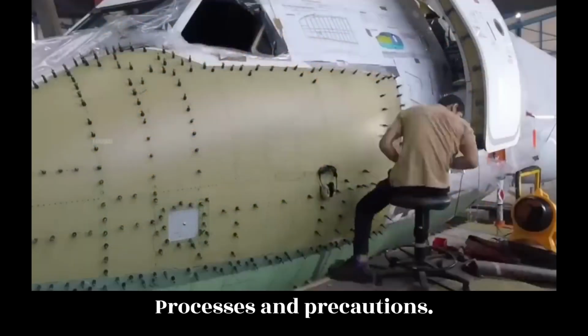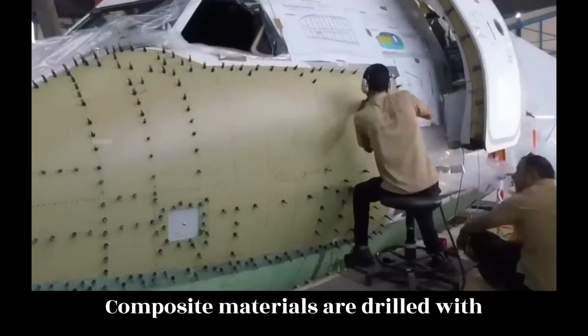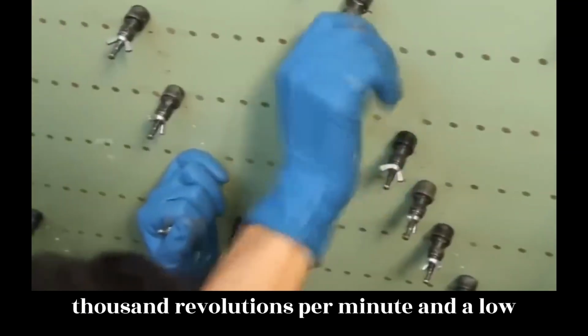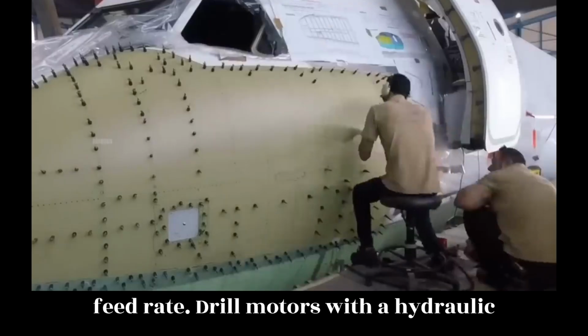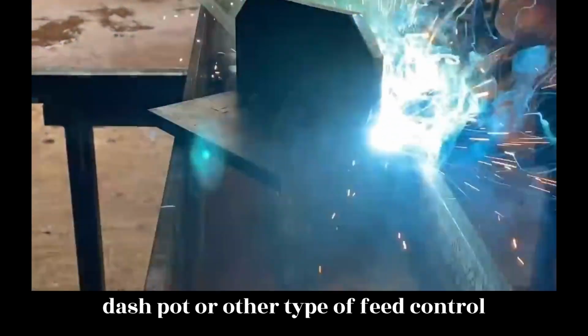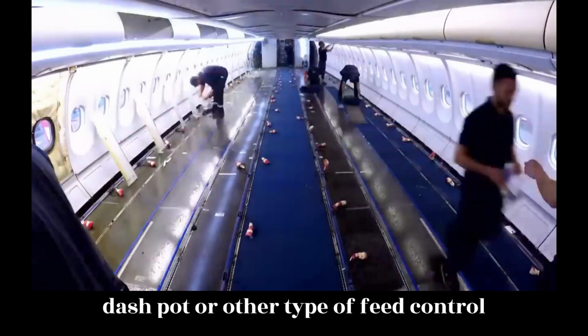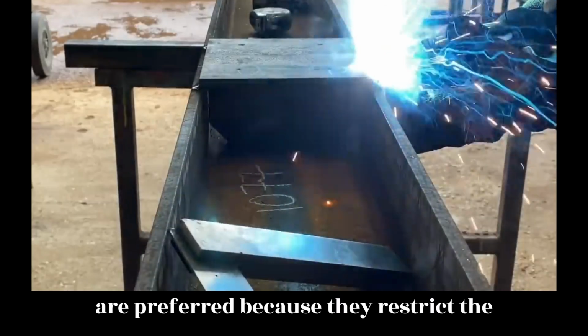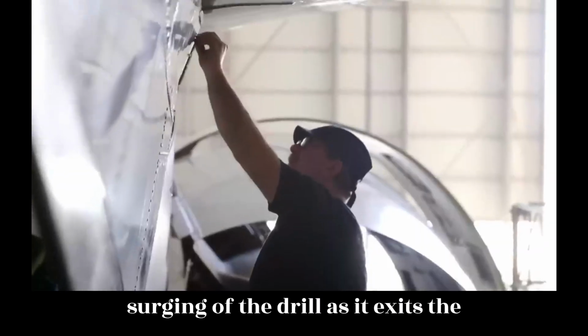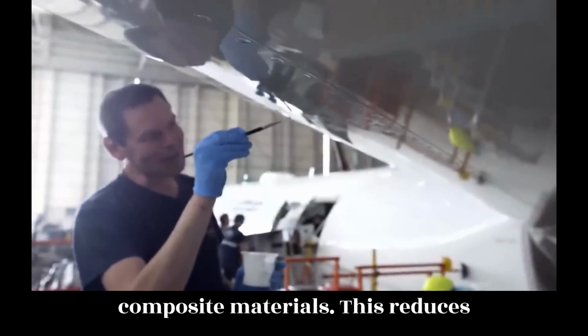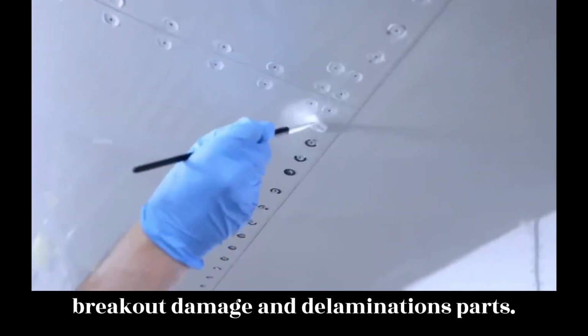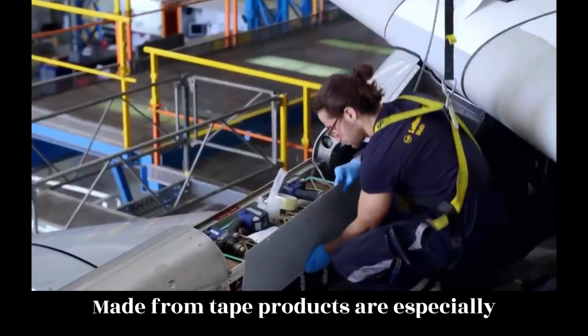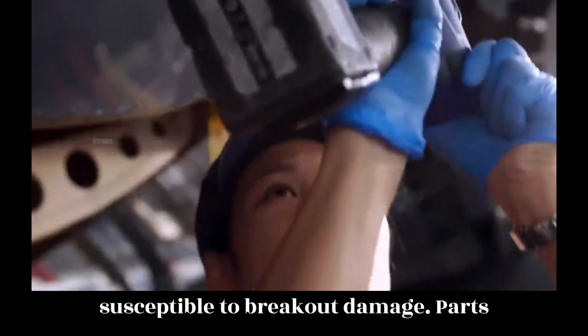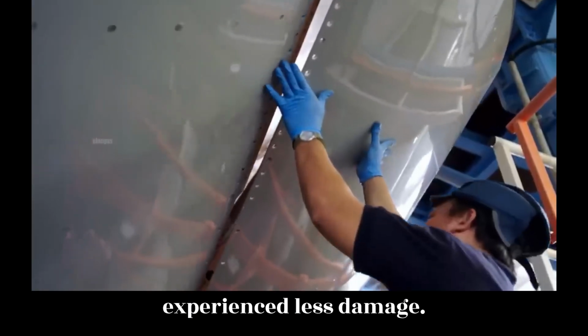Processes and precautions. Composite materials are drilled with drill motors operating between 2,000 and 20,000 revolutions per minute and a low feed rate. Drill motors with a hydraulic dash pot or other type of feed control are preferred because they restrict the surging of the drill as it exits the composite materials. This reduces breakout damage and delaminations. Parts made from tape products are especially susceptible to breakout damage. Parts made from fabric material have experienced less damage.